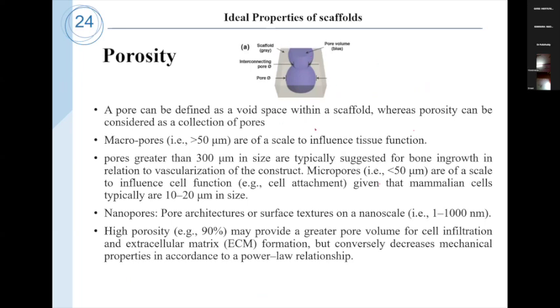So pore size and porosity, these two terms are important in order to support cell growth or tissue growth. For example, macropores, greater than 50 micrometer, are able to influence tissue function. Pores greater than 300 micrometer in size are typically suggested for bone ingrowth in relation to vascularization of the construct. It means the formation of blood vessels. Micropores, less than 50 micrometer, are able to influence cell function like cell attachment, especially for mammalian cells. Typically, these cells are 10 to 20 micrometer in size. That's why less than 50 micrometer is enough to influence cell function. If a scaffold has pores less than 50 micrometer, it is enough for cell growth, especially mammalian cells, which are typically 10 to 20 micrometer in size.